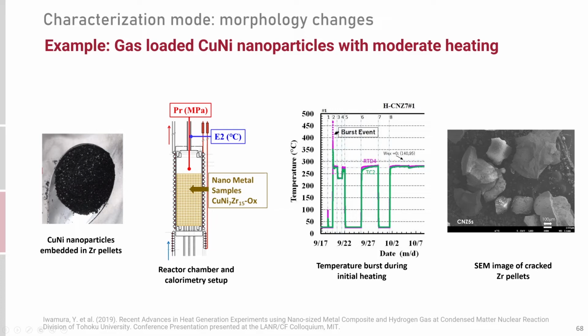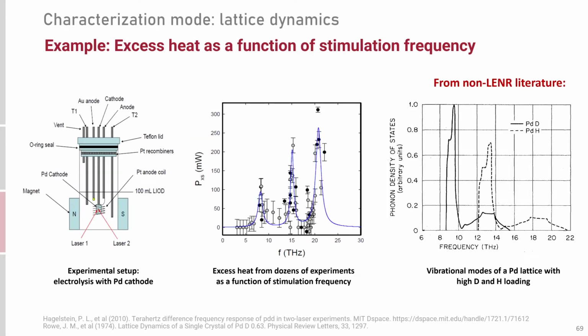Finally, let me show you two examples of characterization modes related to lattice dynamics. In this experiment here, a palladium cathode is in an electrochemical cell loaded with deuterium and stimulated with terahertz photons from a dual laser configuration. Dozens of runs are conducted, each with a slightly different photon frequency. The results suggest that large amounts of excess heat only occur at certain frequencies of stimulation. This graph over here further shows that these frequencies appear to coincide with the vibrational modes of palladium hydride lattice.